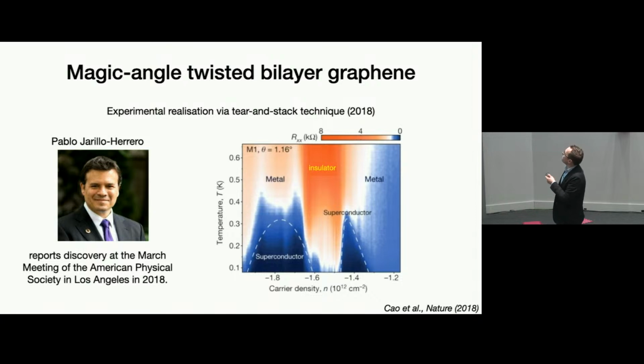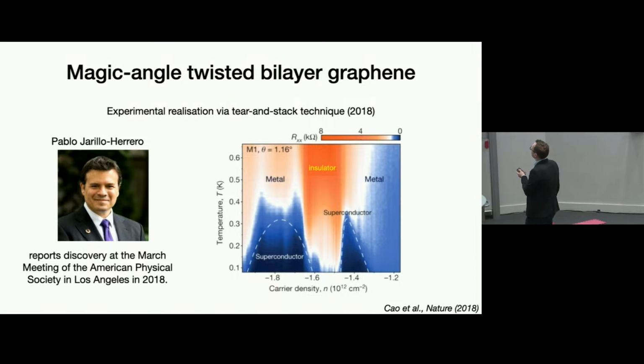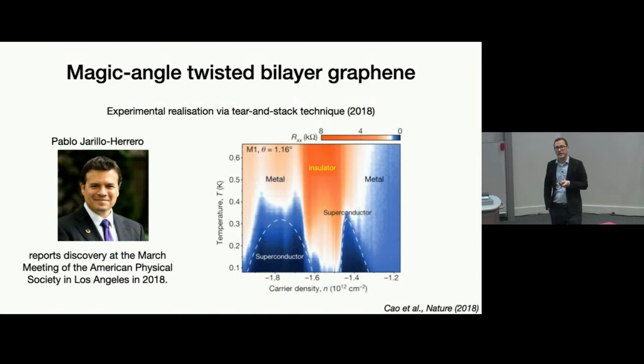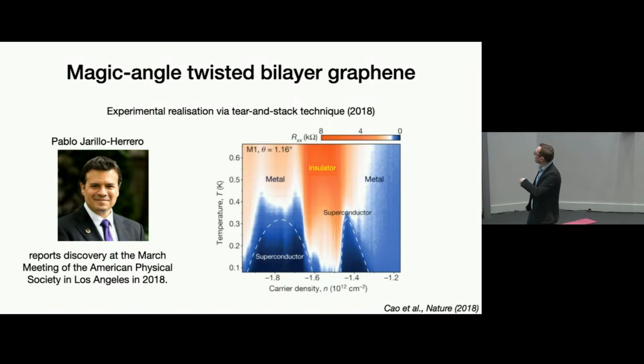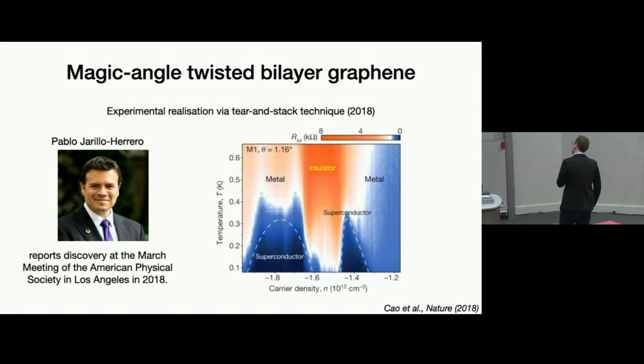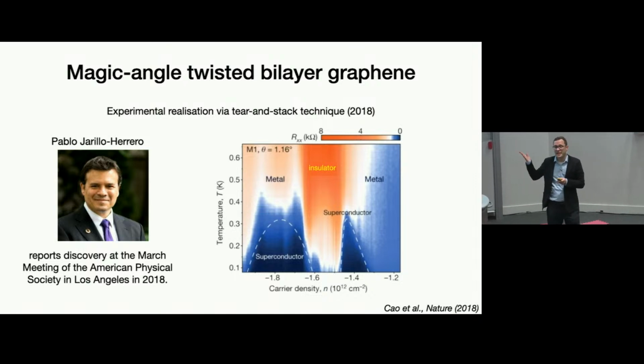And what they measured was, indeed, when you make this magic angle twisted bilayer graphene, it does become insulating. And when you cool it down to very low temperatures, it does become superconducting. So this created a lot of excitement in the community. I was actually at that conference, so I got a little bit swept up with the excitement.